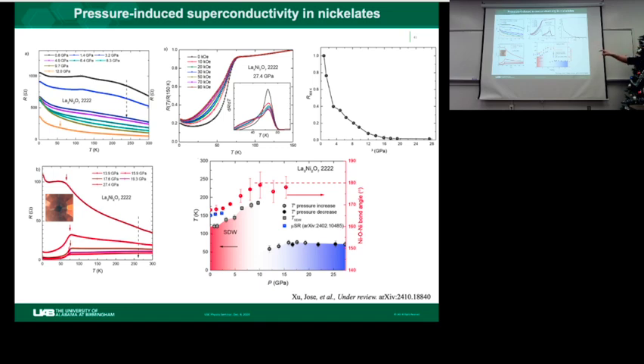And also the question, I think the critical question is why that onset temperature didn't shift at all. It's actually very common for the onset temperature to not shift. Even in cuprates, in many situations, you have only broadening. And actually only a detailed analysis of that curve can give you an idea whether it's due to flux motion in the superconductor.